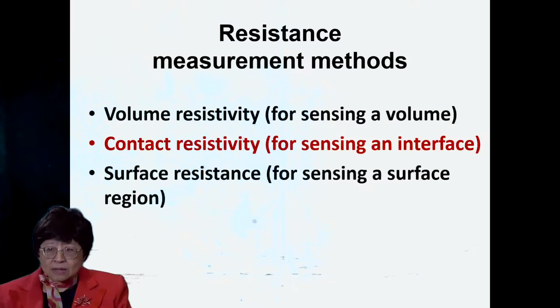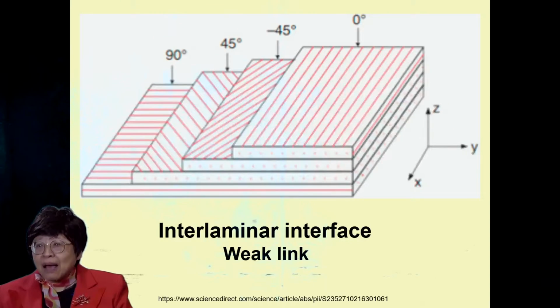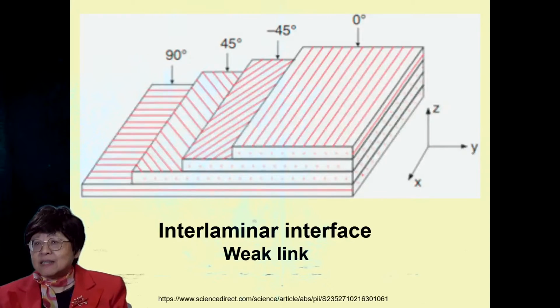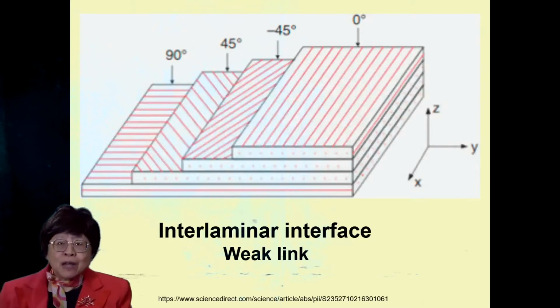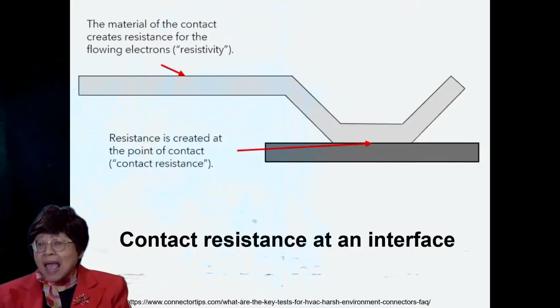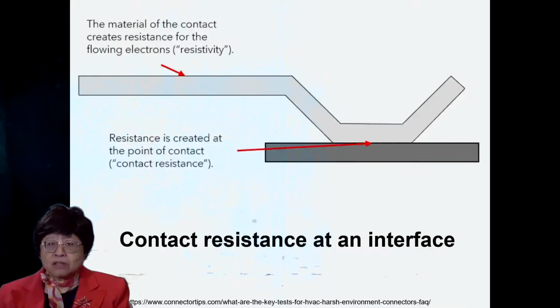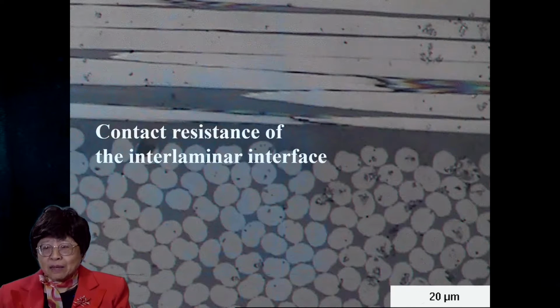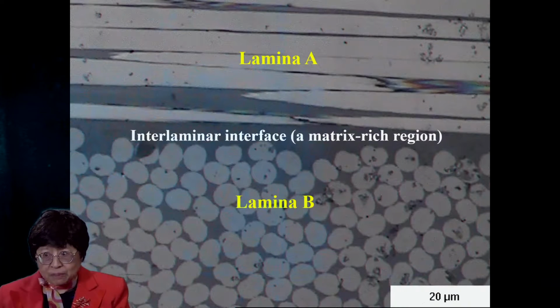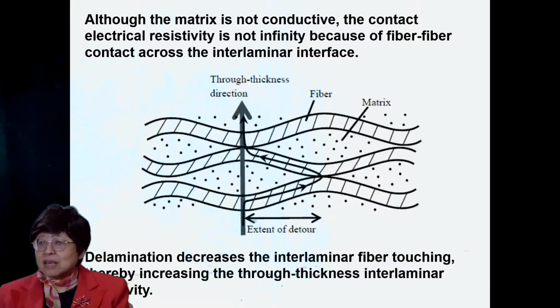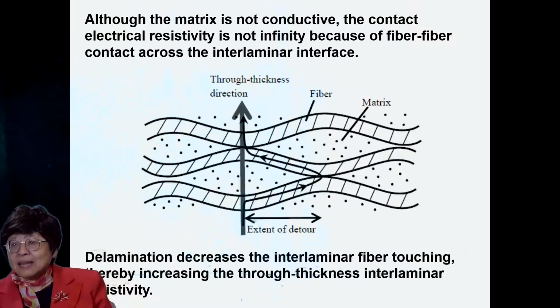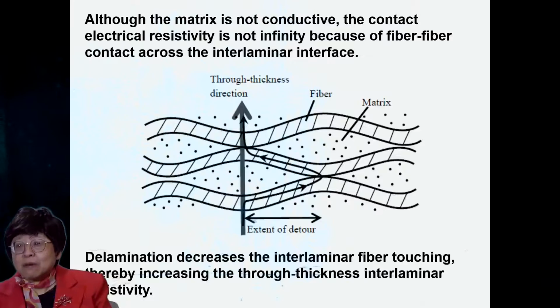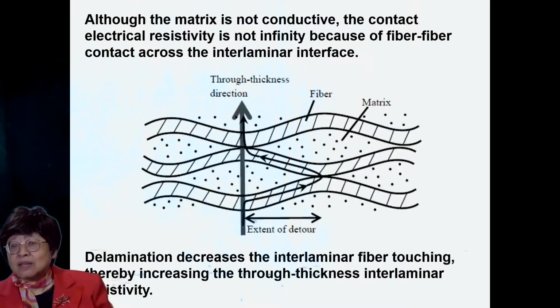Next, let's turn to contact resistivity measurement for sensing an interface. In a laminate, you have plies or laminae, and you have interfaces between the plies. And these interlaminar interfaces are mechanical weak links. Any interface is associated with a contact resistance, and so does the interlaminar interface, which is actually a matrix-rich region. With the matrix being insulating, such as the epoxy, the interlaminar interface resistivity is never infinity because of fiber-fiber contact across the interlaminar interface. And delamination decreases the interlaminar fiber touching, thereby increasing the through-thickness interlaminar resistivity.